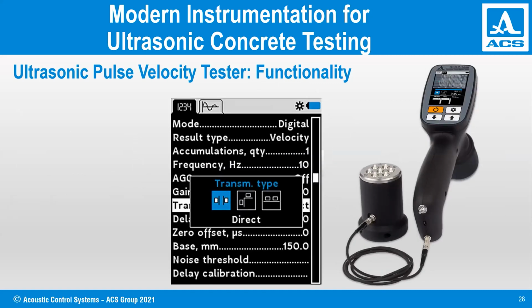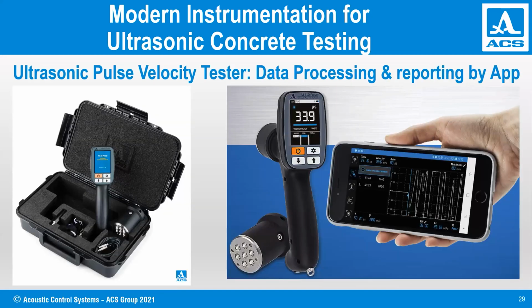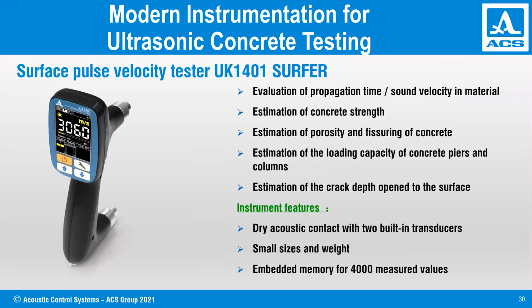So this is how it is implemented in our A1410. Just choose the transmission type, direct or indirect, and then we choose the base value. For example, in this case, it's 150 millimeters. This is the distance between the transmitter and receiver, and we obtain the sound velocity value in meters per second. Or if the instrument is calibrated, we obtain the value in megapascal directly, the compressive strength value. So here I will show a short movie. Oops, I have removed the movie.